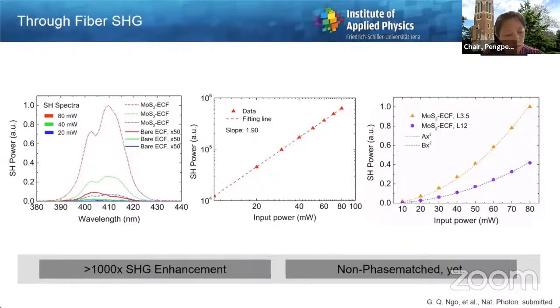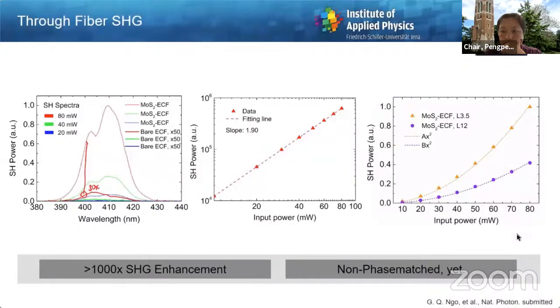we have measured second harmonic in here. So what you see are the solid lines at the bottom, which is the 50 times increased second harmonic spectrum from the bare optical fibers. And then you have the second harmonic from our optical fiber, which is much, much stronger than this. So overall, we observe a more than three orders of magnitude enhanced second harmonic generation as opposed to the bare optical fiber from our coated optical fibers.